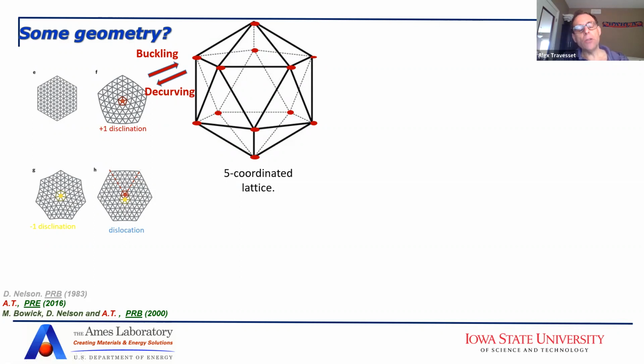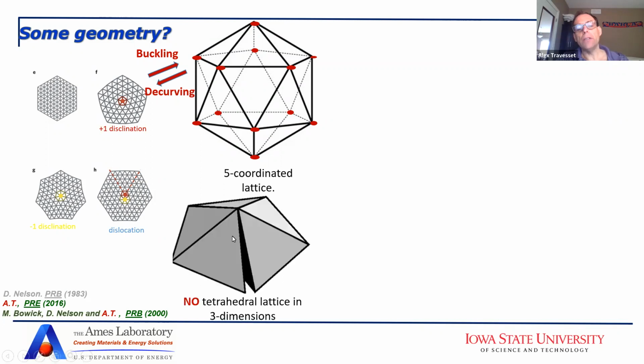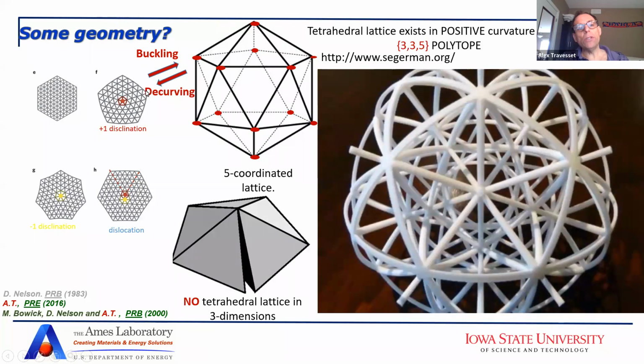The reason why I'm mentioning that is because when you try to do the same idea of a triangular lattice in 3 dimensions, which would be the idea to tile the space with tetrahedra, you start realizing that you form these little gaps, so you cannot succeed. In a way, this is a frustrated system. You can follow the same idea though, and just work in 4 dimensions, and then be able to curve this 3-dimensional structure, and with that you are able to form this structure which has 600 of these tetrahedra, and is the 335 polytope. This is actually a conformal projection.